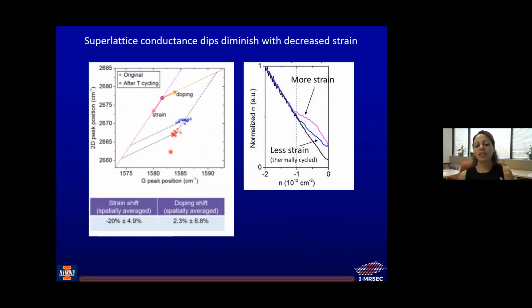And finally, we showed that when we thermally cycled these... Now again, we've just pressed the graphene on, and so when we thermally cycle it, the graphene can slip a little bit and relax, right? So what we expect is, with thermal cycling, we get reduced strain. And indeed, that's what we see. When we thermal cycled our sample, this on the left here is our original sample. It's pretty highly strained. And then we heated it up and cooled it down again. And when we did that, it reduced its strain. Okay, it went to there.